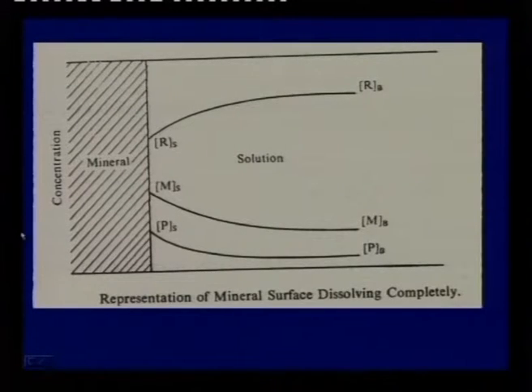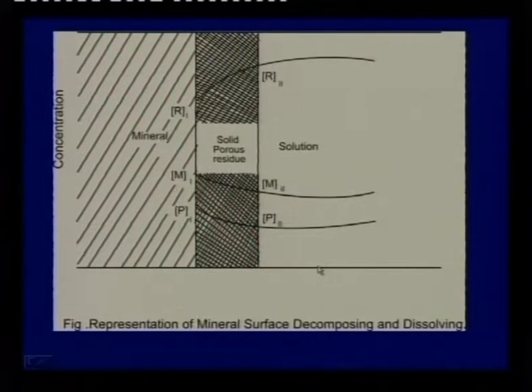I tried to show how kinetics can be applied in analyzing leaching reactions. Here is a solid mineral surface which is reacting with a leaching medium, and we see the reagent concentration from the bulk getting depleted when it comes to the surface. It is coming this way. Metallic values that dissolve at the surface diffuse out into the bulk, and when they diffuse out, there must be a concentration profile going down. The concentration must be increased here. If there are some other products, residues, apart from metallic values which go into solutions, this would also have a concentration profile. If there is a solid porous residue, then the diffusion processes take place through that residue.